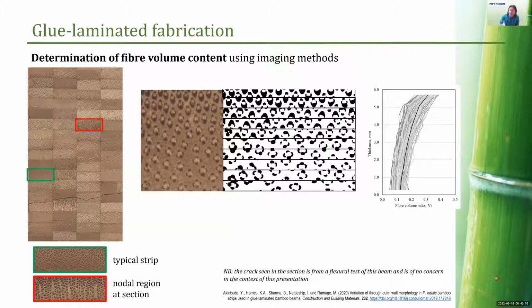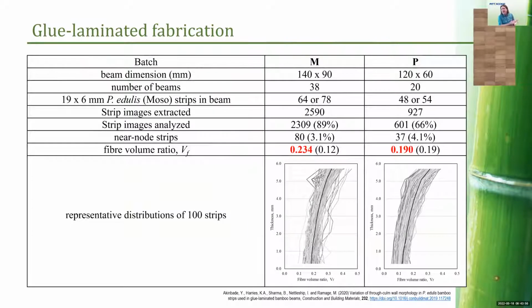And this particular plot just shows 100 different strips. So in this study, we looked at 2 different materials. We'll call them M and P. The beams are very slightly different, 140 by 90 versus 120 by 60, but they all have the same 19 by 6 millimeter strip dimensions. We looked at about 60 beams all told and extracted almost 3,500 images, of which about 3,000 were usable. You get blurry images. You can't extract every image, but we have a remarkably large data set.